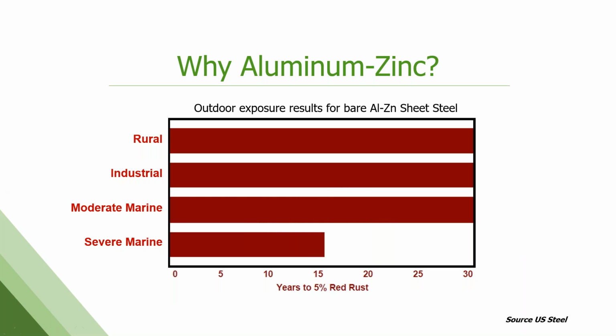So this is years to 5% red rust, kind of an industry standard, in different environments like rural versus industrial, moderate marine, and severe marine. And you can see that even in a severe marine, so this would be like constant saltwater spray, it still is going to be 15 years before you get any kind of noticeable and appreciable red rust on this product versus galvanized, and 30 plus in less severe areas.